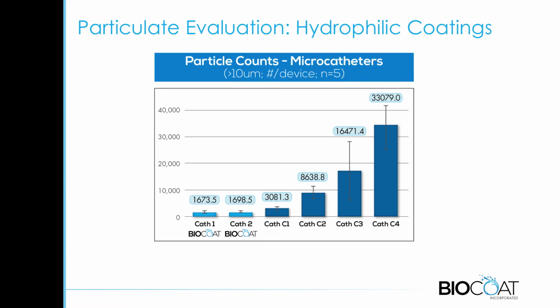Looking at the particulate evaluation for these hydrophilic coatings, we're looking at it two different ways. One is looking at the total particle counts from these microcatheters. So it's the number of particles greater than 10 microns for the entire device. And you can see that there's a rather dramatic difference between the various coatings. The one that was catheter C4, which didn't have much of a great durability, also not terribly surprising, has some rather high particulate generation. Some of the ones, say the Biocoat ones, had very low particulates, and even some of the other ones had about twice that. But other ones also had some rather higher values, 10x higher than some of the best-in-class ones.